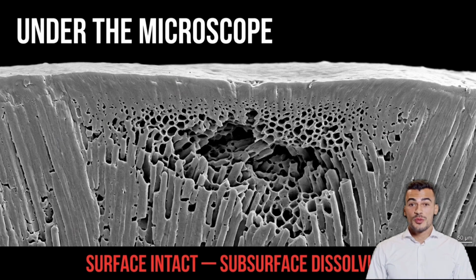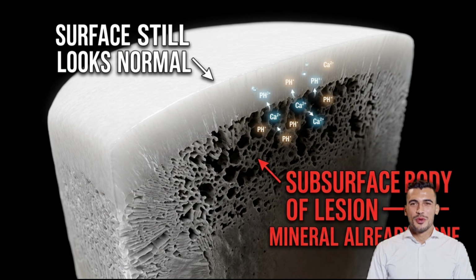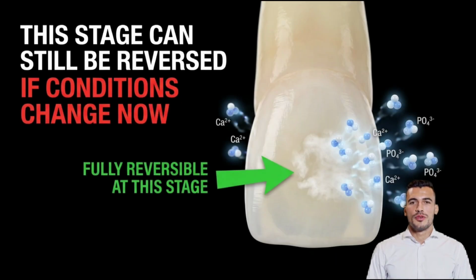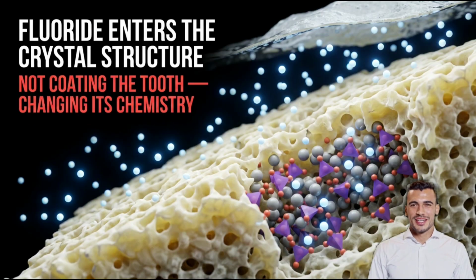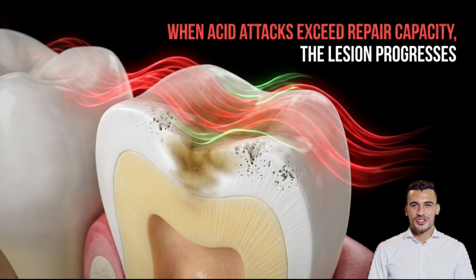There is no hole yet, no visible damage. What you see instead is a change in the crystal structure of the hydroxyapatite. The tightly packed mineral rods begin to show microscopic spaces between them. The subsurface layer of enamel begins to lose density, while the outermost surface, still in contact with saliva, may appear intact. This is the white spot lesion, the earliest clinically visible sign of caries, a chalky white patch on the tooth surface that most people mistake for staining. At this stage, the lesion is fully reversible.